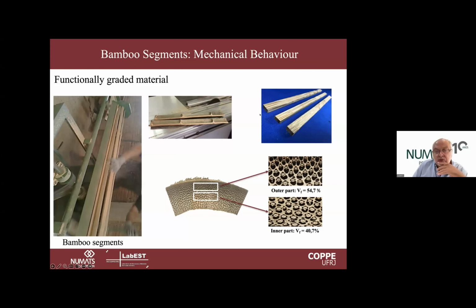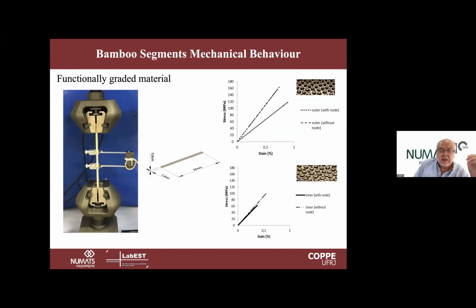Also, the presence of nodes influences the response of this material under direct tension, under bending loads. So what we see here is that the presence of nodes, in general, reduces a bit the elastic modulus and the tensile strength of the bamboo strip, both when they are taken from the outer part and from the inner part. And those that are taken from the outer part have about 20-25% more strength because they have more reinforcement.